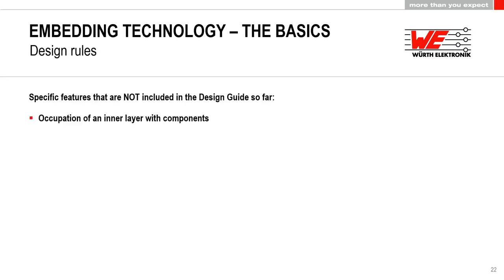Then there is one point about inner layer occupancy. How many components can you fit onto the inner layer? Normally we say, please, not more than 40% of the available area. Why is that? You've seen in the process flows that we need to fit FR4 material beside the components so that resin can flow into the cavity.